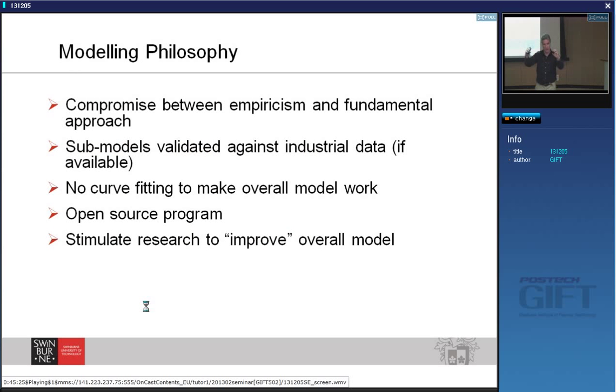And I want to make something very clear to you. We didn't do any curve fitting. We developed the models and then we predicted the process. We didn't fit them together. You know that if you put K in front of every single equation, you can make everything fit, all right? Do you know that trick? If you have five equations and you put K in front of them, K1, K2, K3, K4, K5, you can make anything. You can make it look like a map of Korea. You can make it look like the inflation rate. You can make it look like anything you want. That's called curve fitting. We didn't do curve fitting. We made the models and pushed the models together and saw what we could predict.